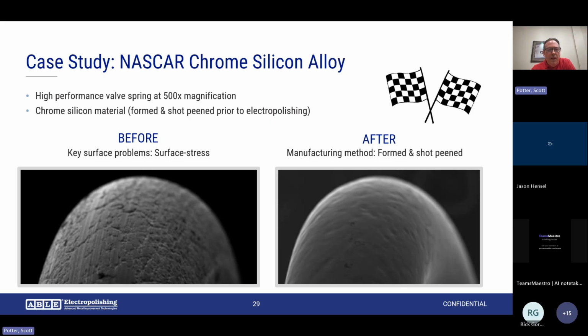You can see how the electropolishing moves. We call it the notch effect. When you're forming springs, from the stress of forming, you have a tendency to create little notches, little imperfections in the surface. With electropolishing, you see where it typically improves the microfinish by up to 50%. It removed some of the minor imperfections that might lead to premature failure.